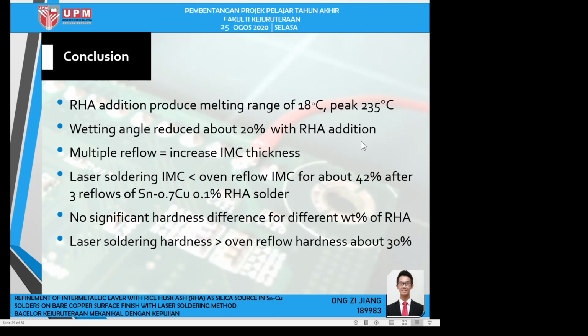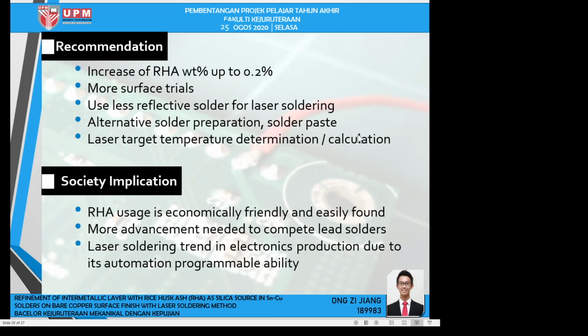And there is no significant hardness difference for the different weight percentages of RHA. However, the laser soldering hardness value is higher than the oven reflow hardness by about 30%. Next, the recommendations are that maybe we can try increasing the RHA weight percentage up to 0.2%. Maybe we can have more surface trials. Maybe we can have less reflective solder for laser soldering, an alternative solder preparation such as solder paste, and maybe we can try laser target temperature determination.